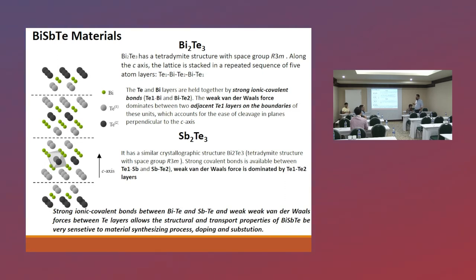Anyway, thank you very much for the great questions. I have one or two. Following Kazu's comment, I also believe that 0.1 to 0.5 is too much, but this is the nominal composition, not what is actually put in. Probably during the ball milling you lose most of it, and the actual content is, I am sure, lower than 0.1. Doping efficiency is much lower than what you put in.